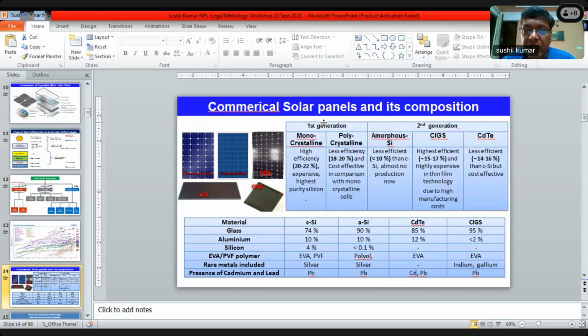In the case of amorphous silicon, it is not produced that way. It is produced in a vacuum chamber as a thin film on some supporting surface. Like on glass, you have to grow the amorphous silicon layer using plasma. Here SiH4, the gas, is used so that you can have a silicon thin film. The advantage of silicon thin film is that a very thin cell layer is needed, hardly 1 micron or so, but in bulk silicon, that is monocrystalline or polycrystalline, 200 microns is needed. But since efficiency is not getting a boost in this, it has somehow lost its market share.